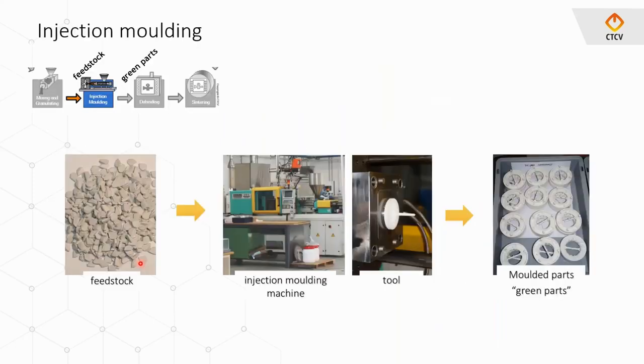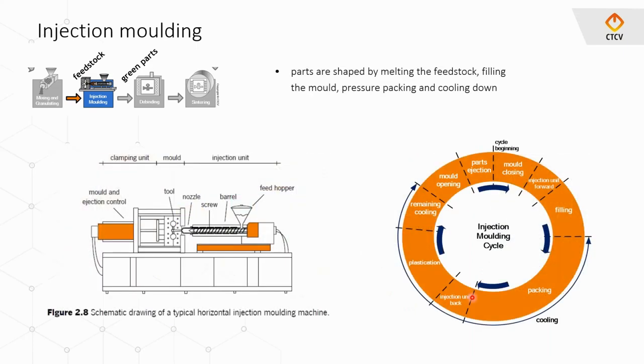So in the injection molding step, we process the feedstock by melting and cooling down inside the tool. And then we get the green parts, the molded parts, after this step. The injection molding can be performed with this kind of machine. In this scheme, we have a high pressure injection molding machine, which is very similar to plastic injection molding machines. We have the tool inside, and we have the plastification unit here.